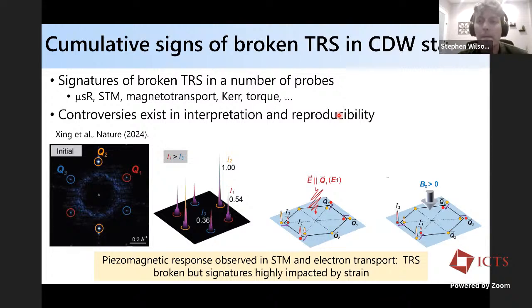But I will say there have been two recent results which can perhaps address some of the reproducibility issues. The first I'll highlight is some very beautiful work by Vidya Madhavan's group at the University of Illinois Urbana-Champaign, where they looked at the rubidium variant. They looked at the charge density wave phase on the surface of the system and Fourier transformed that. When you do that, you can see the charge superlattice peaks that come from the CDW phase, which have inequivalent Fourier weights. So you can define a winding that goes from the highest to the lowest in terms of these three inequivalent endpoints.